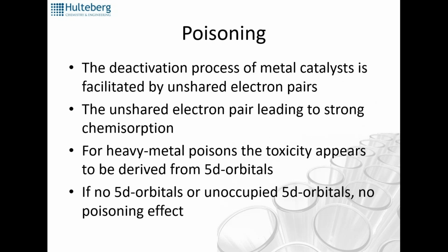The deactivation of metal catalyst is usually due to pairing of unshared electron pairs. So these unshared electron pairs do very nice and very strong chemisorption to the metal. And when it's very strongly adsorbed, it won't desorb and it won't leave space for other materials to react on the surface. But it's not just that it blocks one single site. Since it's strongly electronegative, it will also impact other active sites around it.